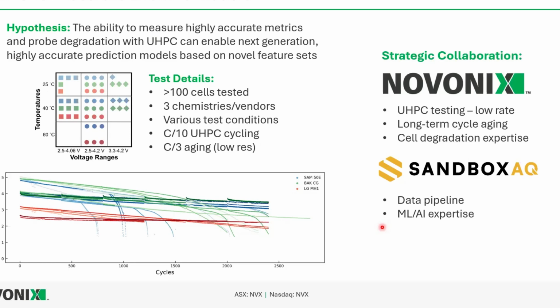So this is a case study that we did with partner Sandbox AQ, working with a couple of different cell chemistries or cell vendors, with cells with all high nickel cathodes but different anodes. Some of them contain only graphite, some of them contain graphite and a bit of silicon, operating at different temperatures and different voltage ranges to turn on and off some of the failure mechanisms, to make it really hard to make a generalizable model for lifetime prediction.